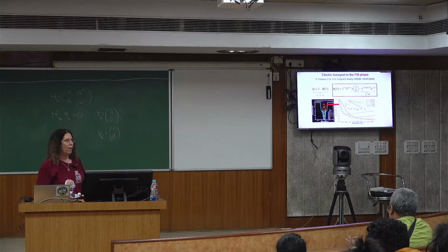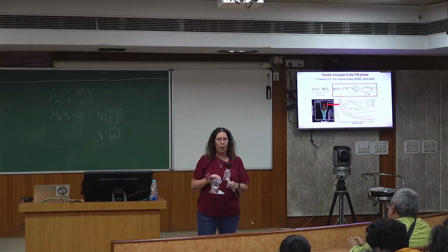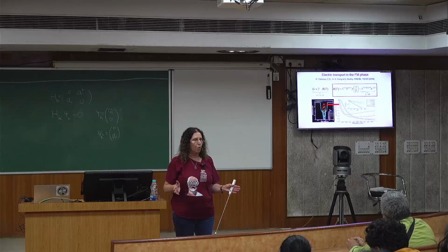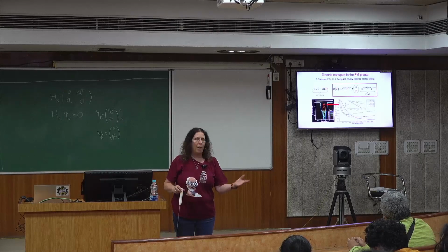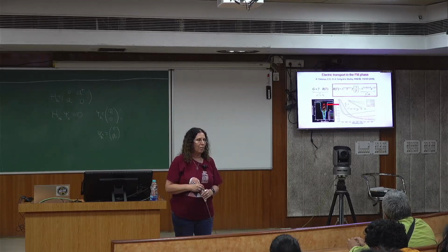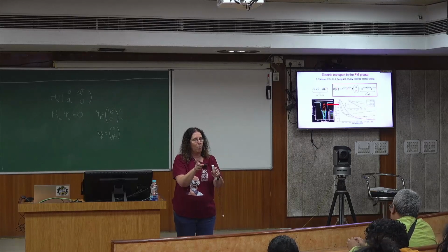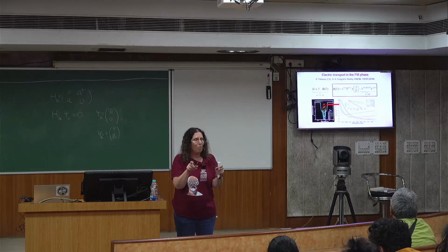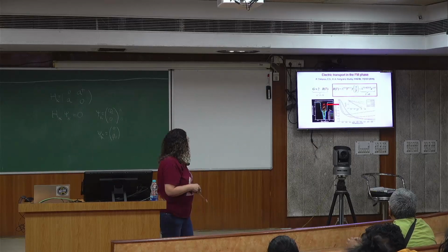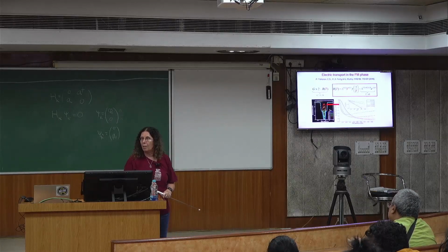So basically it seems like the ground state of the nu equals 0 quantum Hall state in graphene is most likely a canted antiferromagnet. We don't have any spin-sensitive imaging to prove it, and it would be very hard to do because this antiferromagnet is on a lattice scale. Okay, it's angstrom. You need something with resolution of angstrom to actually see it. But if you just look at the transport, it looks consistent.